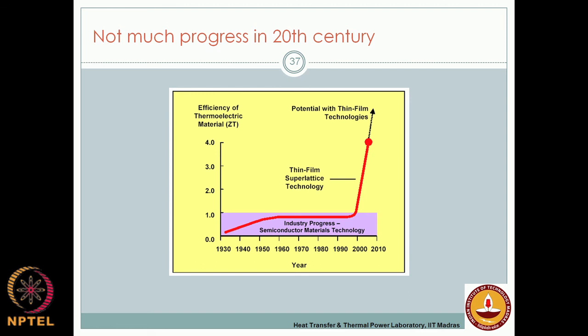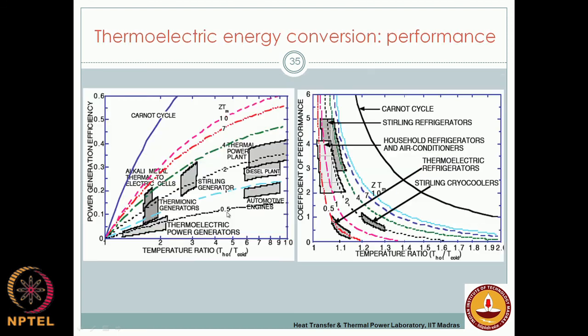Okay. So, this is where the nanoscale materials play a role for thermoelectrics, because what you see is the value of ZT plotted on the y axis over a period of time, and you see as long as you are using bulk semiconductor materials. Okay. So, you are not getting a value of ZT above 1, okay, and you see the value of ZT of 1 will give you an efficiency which is always less than 20%.